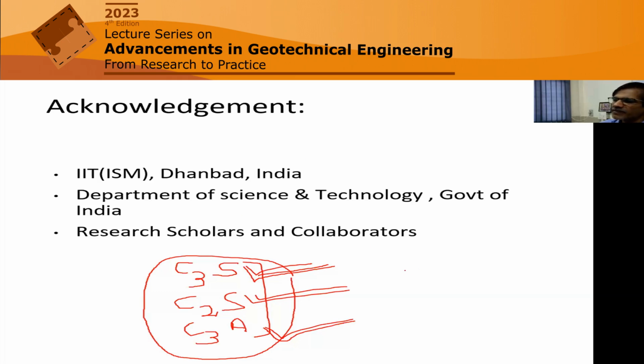Whereas when it comes to fly ash, particularly high calcium fly ash, which is the only cementitious one, in the high calcium fly ash there is a chance that a lot of it is free lime. The free lime is not good. That creates the soundness problem. That means if its content is more, it may crack in the long term. But in some high calcium fly ash there are also minerals similar to C3S, not exactly C3S, available. So that is responsible for the strength.